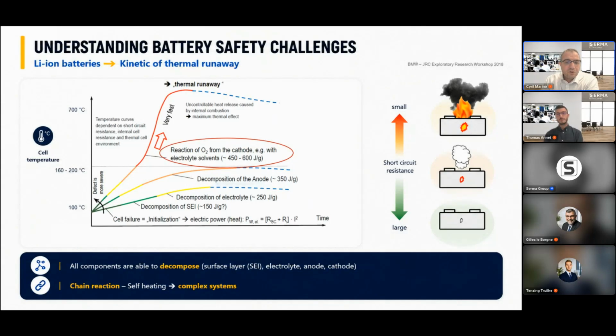And this depends on the cathodes that you have in your system. Either you go to 400 to 600 degrees, or you go even beyond this, at more than 1000 degrees, depending on if your cathode itself is able to produce oxygen in your system. This is the case, for example, of NMC cathode versus LFP, where LFP will not produce oxygen. So this shows you that the reaction and also the components that are inside the cell are really critical, and the reaction at the end depends strongly on these parameters.